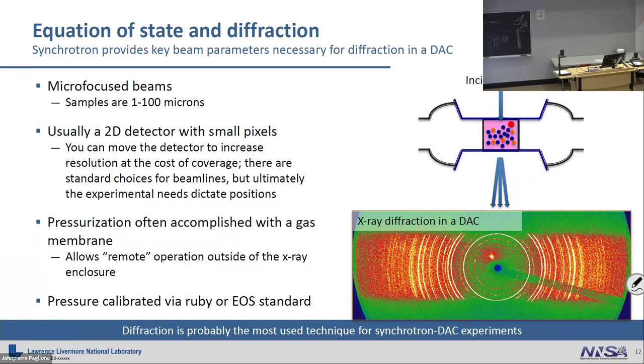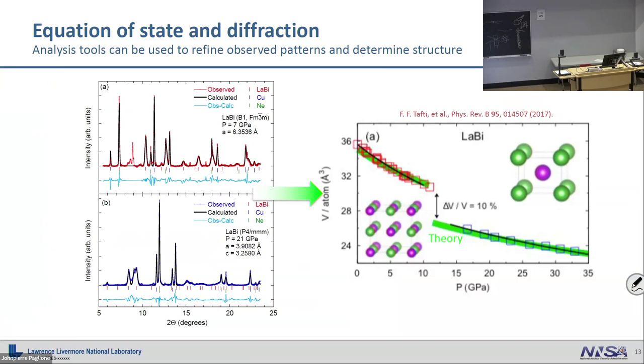And the reason I like that in the pattern is because it tells me what the pressure is in the pattern, where the beam actually is. So in general, I would say the best thing is to avoid having your calibrant in little pockets separately, because you don't know about pressure gradients, things like that. So having it in the pattern is actually quite useful. You have to be careful about what you pick as a standard to make sure it doesn't overlap with your sample, because then you can't necessarily measure it. So you need to do some planning of that, but it's very nice to have in there.